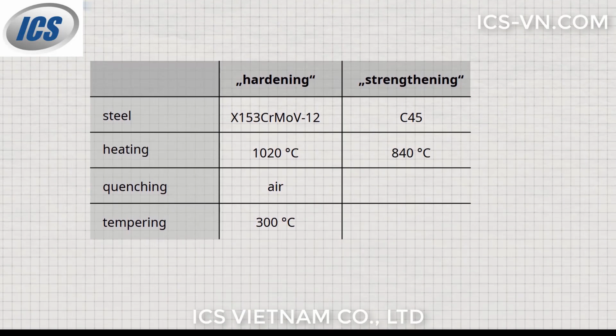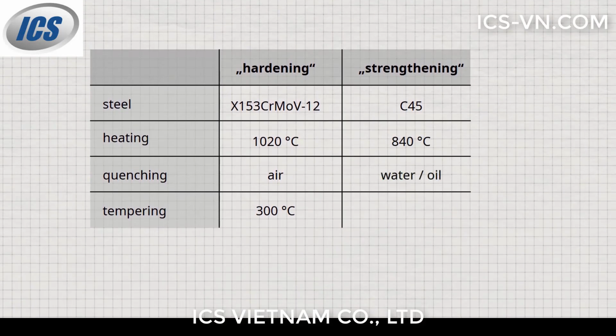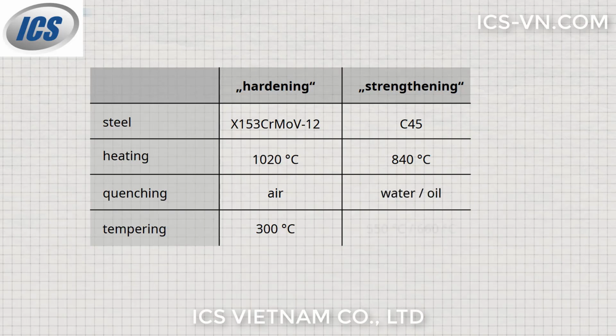This unalloyed steel is then quenched in either water or oil. After quenching, the steel is tempered at 550 degrees Celsius if quenched in water, or at around 660 degrees Celsius if quenched in oil.